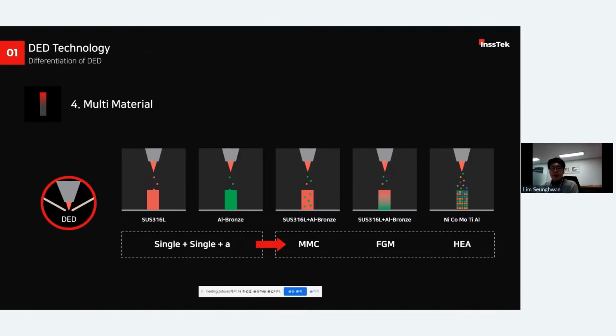Last feature is multi-material. Since the process is performed continuously supplying metal powder to the molten pool, if the metal powder is changed during supply, several different materials can be stacked partially in one process. With this feature, multi-materials can be used in various ways, such as bonding of dissimilar materials or gradient materials. It is DED method's own advantage that it is not available with other 3D printing methods. It is impossible to control the composition of the material in shape of wire or powder layer.